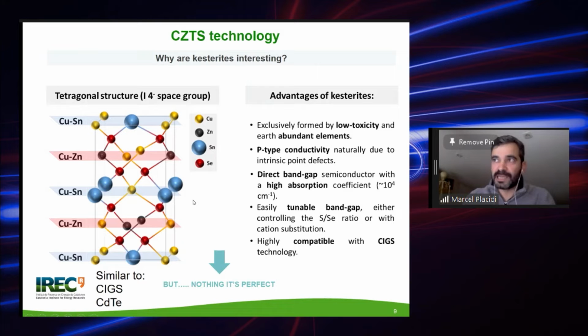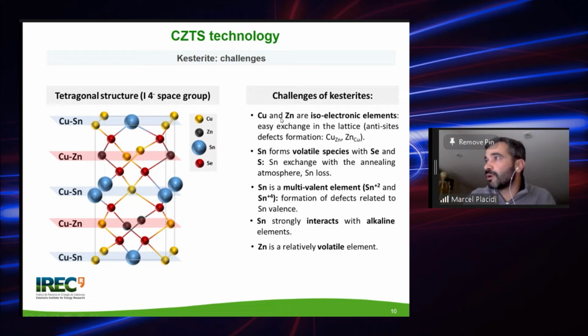Okay, but this material is not perfect for the moment, because since it is formed from many elements, many defects can be formed. In particular, for example, copper and zinc are isoelectronic elements, so they substitute themselves very easily, and there is formation of anti-site defects, copper on zinc and zinc on copper, which are very easy. Tin also is very volatile, and it has a tendency to be lost during the thermal annealing, during the formation of the kesterite. Tin is also a multivalent element, and this is probably the main reason advanced until now for the low efficiency achieved to date. Because there is a lot of formation of defects related to this multivalence of tin.